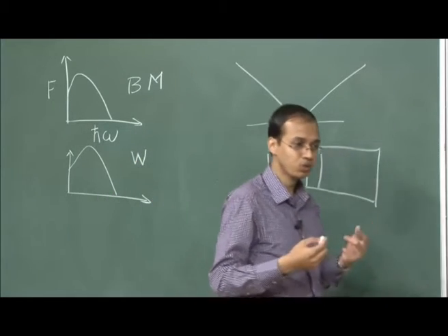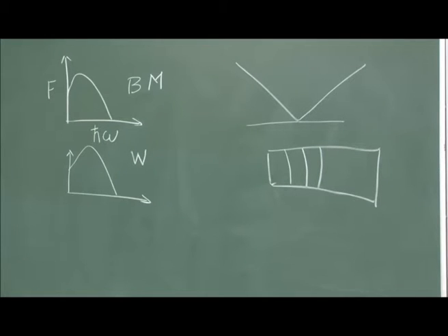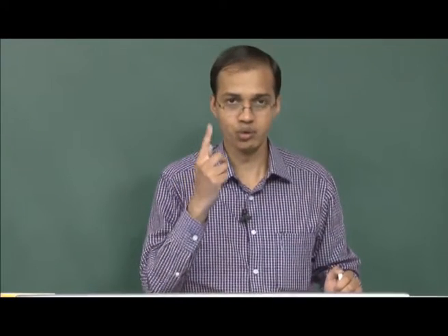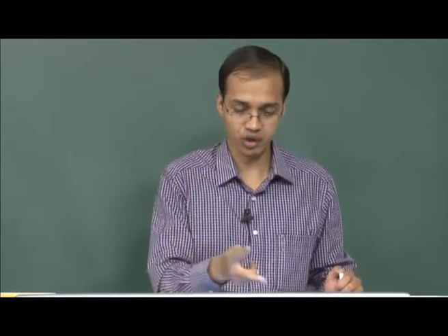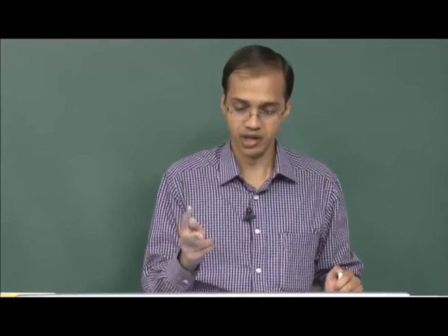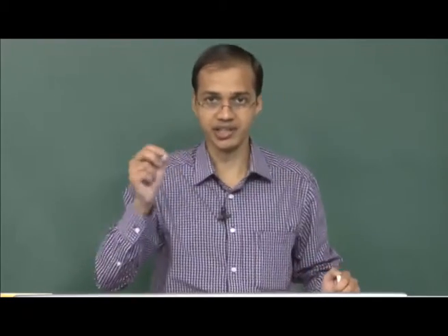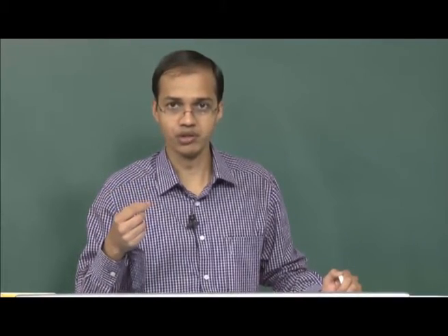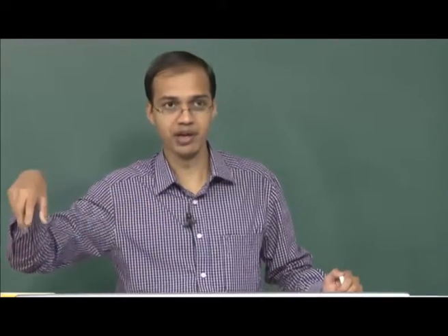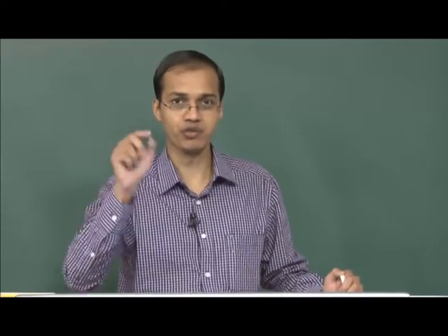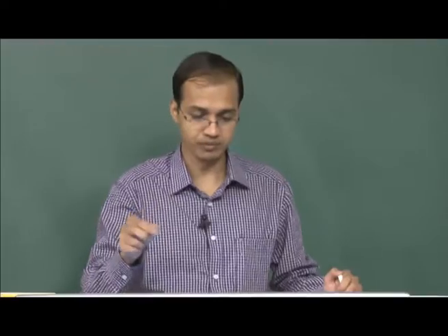Now, I will go back and show you the state of the art detectors which can count the X-ray signal and convert it to an electronic signal. So, we have what is known as a single photon detector, which reads only one theta or one angle at a particular time. This comprises the normal scintillation detector made of sodium iodide, where on hitting the X-ray we get the emission of a photoelectron, which is then passed through a photomultiplier tube to generate an electrical signal, and this electrical signal is proportional to the number of X-ray photons hitting the sodium iodide